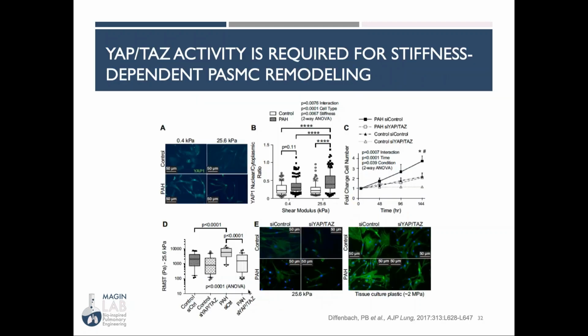So here they have used pulmonary artery smooth muscle cells, and they've shown that YAP-TAZ activity is required for stiffness-dependent remodeling in these cells, and they've done this again using a polyacrylamide hydrogel base. They've also shown that cells that came from a pulmonary arterial hypertension or PAH patient are inherently more active on these surfaces, whether they're soft or stiff, than the control cells. So you can see in the PAH cells that you have nuclear YAP here, even though it's being grown on a soft material.